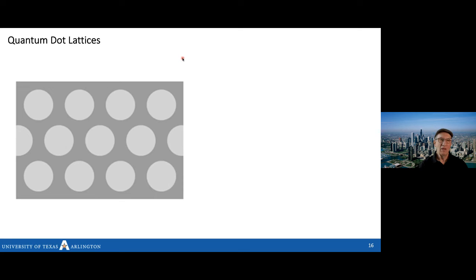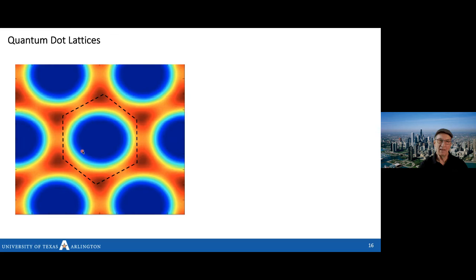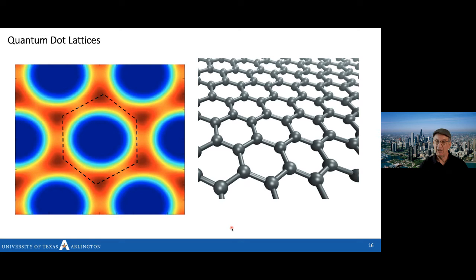So what we realized is that if we take this quantum dot lattice and form a hexagon, and then look at the analysis around the hexagon, this looks like a benzene ring. And the corners of the benzene ring are where the carriers are most concentrated. It's sort of, by analogy, looks like this, which is a planar single atomic layer crystal. And if you don't recognize this, this is graphene. And graphene separately is a source of a lot of interesting research and commercial applications.